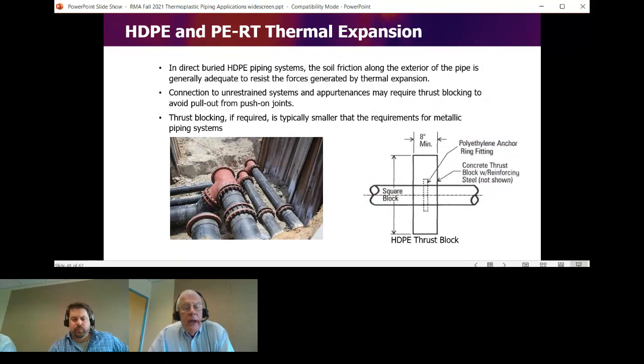One area that you need to pay attention to is at connections to an existing system. If you're connecting to an existing ductile iron system that is not joint restrained, and you have a long section of HDPE coming into it, you may have to put a restraint on the interconnection so you don't pull the joint out when the HDPE shrinks.